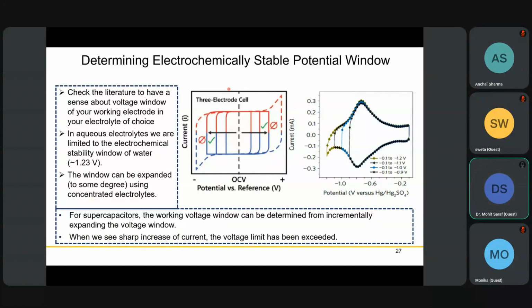If you want to get a sense of your electrochemical window, you can slightly increase the potential window on both sides until you see a sharp tail on both ends. At this point it is still okay, but after this point you will start seeing sharp peaks, maybe a redox peak, so I won't mind killing my first cell to find out.